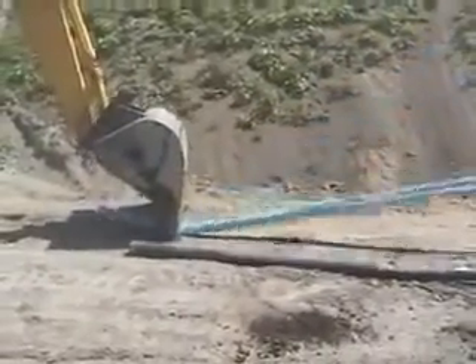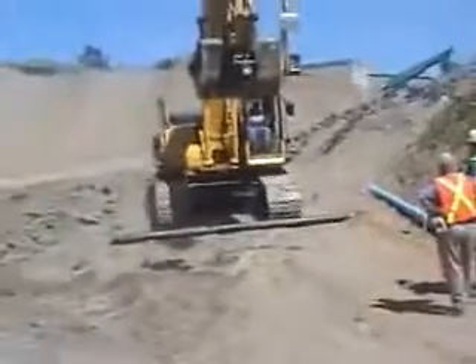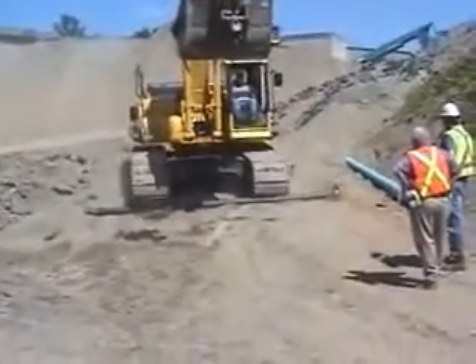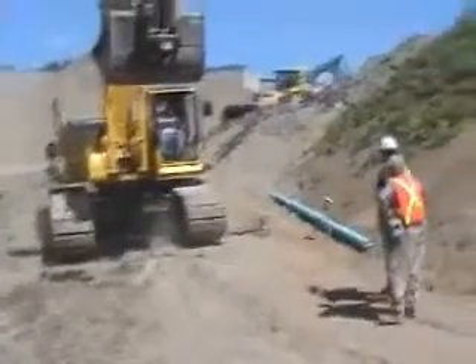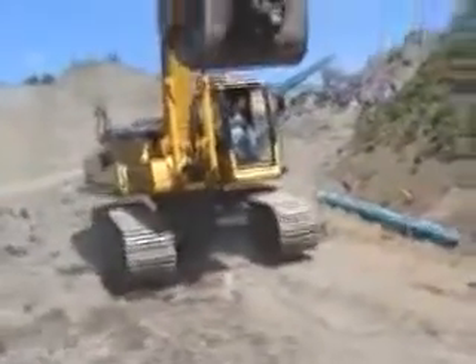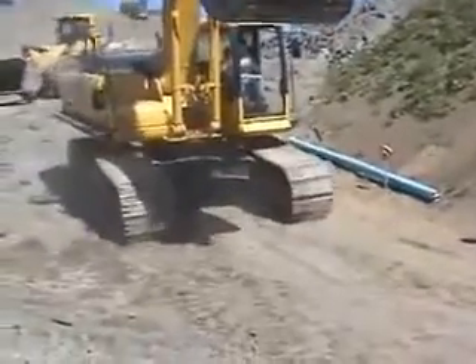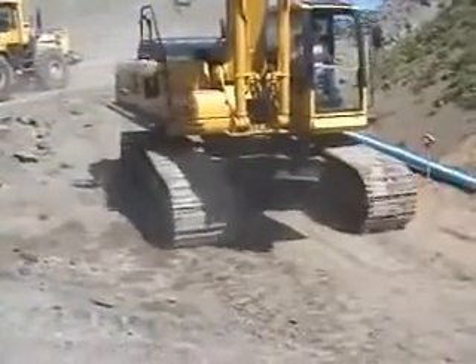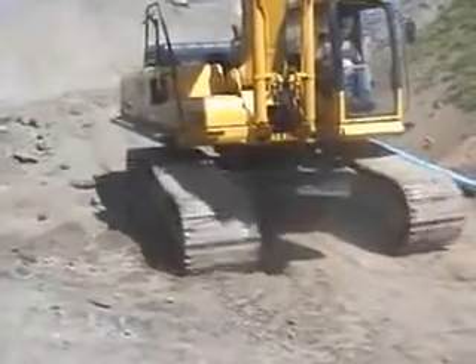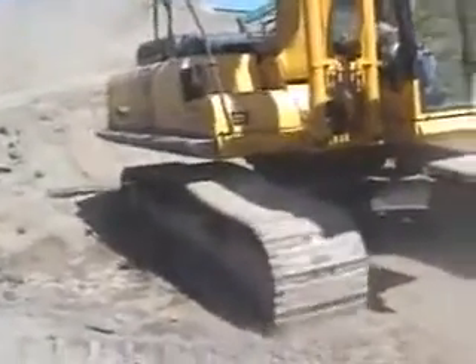Bionax was then put under additional stress by hitting it with the blade of the bucket. This did create a stress mark on the pipe. Ductile iron was not subject to this additional test. The final portion of the demonstration involved running over the pipes with the Kobelco 370. The ductile iron experienced catastrophic failure in this test.